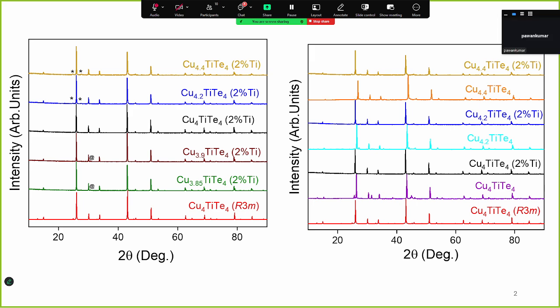Yeah, just check with the handheld system whether the Seebeck coefficient can change or not. No, but there's no pellet. It's still powder form. Okay, I mean, you can compact it, cold press the powders and just check the Seebeck coefficient. No need to bother about conductivity. Yeah, you can cold press.